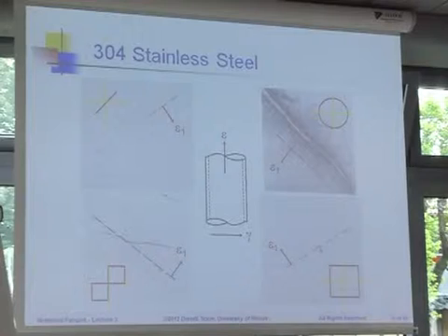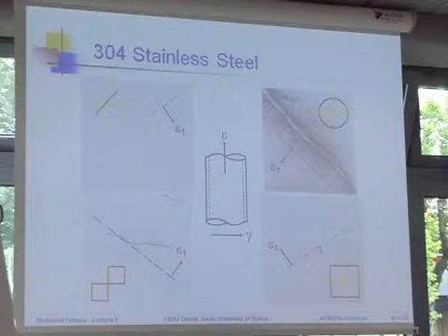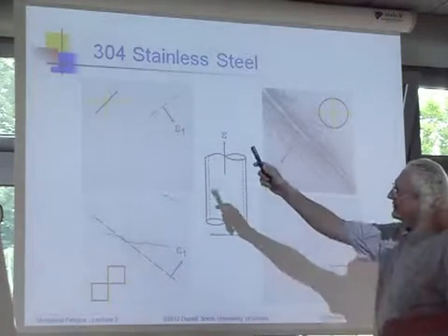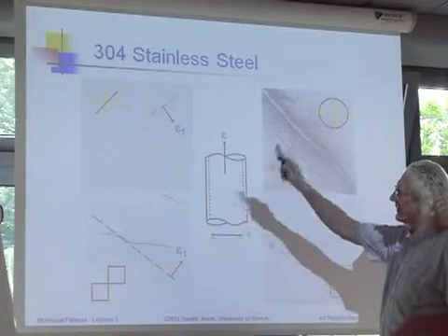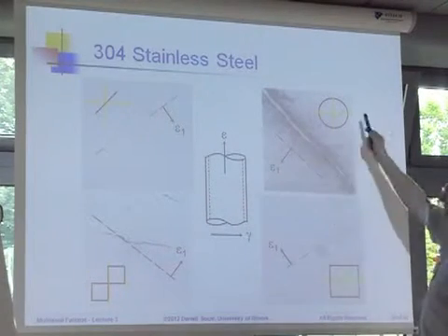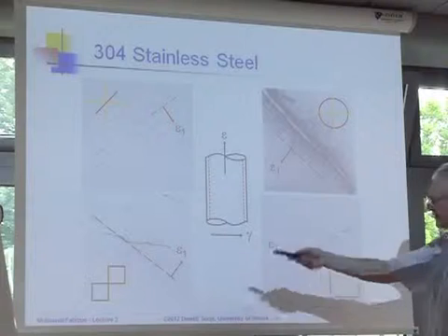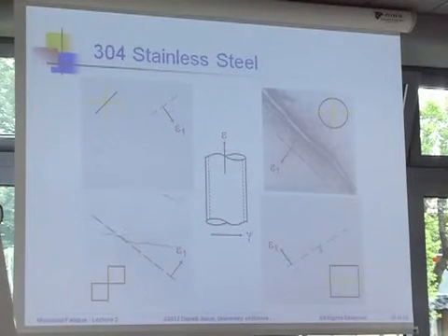As what I alluded to before, not all materials nucleate microcracks and grow these microcracks in shear. This is what happens to stainless steel. And so here are 4 different loading paths, and again, this is tension strain in this direction, shear strain in this direction. Here's these out of phase paths, and here's a box, and here's that. And what you see is that stainless steel, one of the most ductile materials we have, actually fails because of the growth of cracks on principal stress directions.